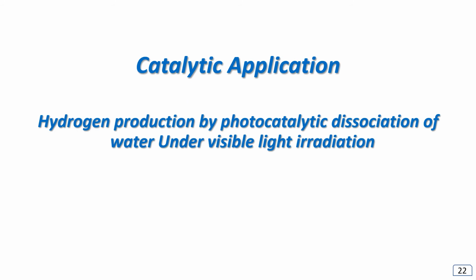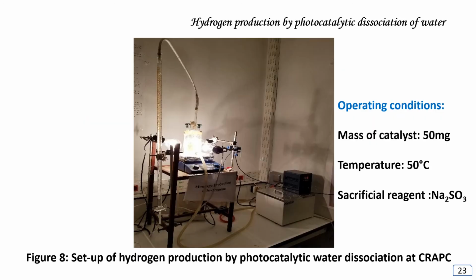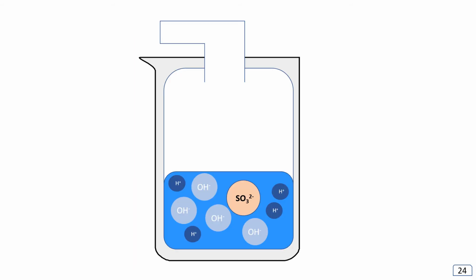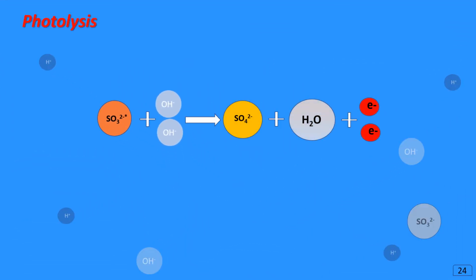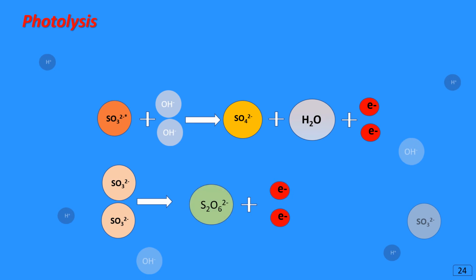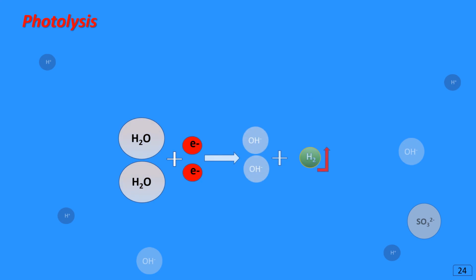The catalysts synthesized in this work were used in the production of hydrogen by photocatalytic dissociation of water under visible light irradiation. The test was carried out in a pyrex reactor under these operating conditions. Under irradiation, two types of phenomena occur: photolysis and photocatalysis. Under irradiation, the sacrificial agent is excited and then oxidized by hydroxide anions to give SO4 2-, water and electrons. SO3 2- is oxidized to give S2O6 2- and electrons. The electrons produced before will reduce the water to give hydrogen and hydroxide anions.